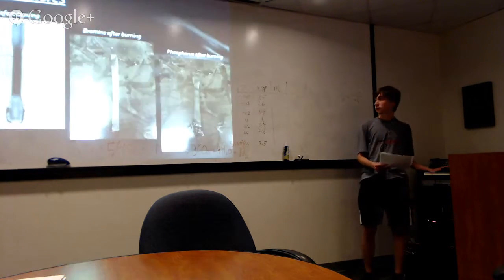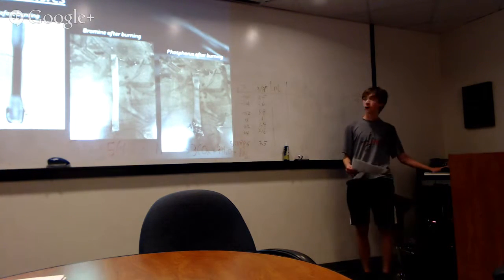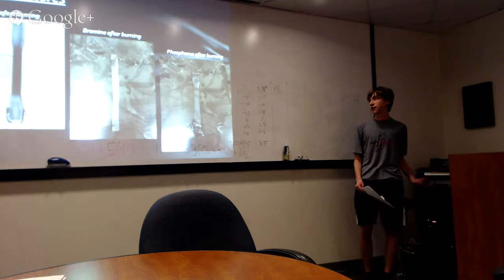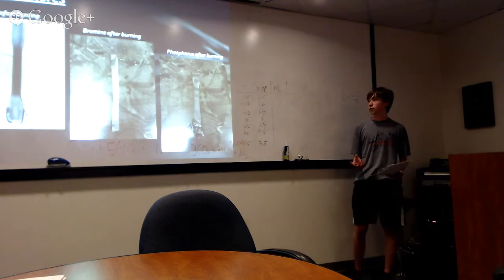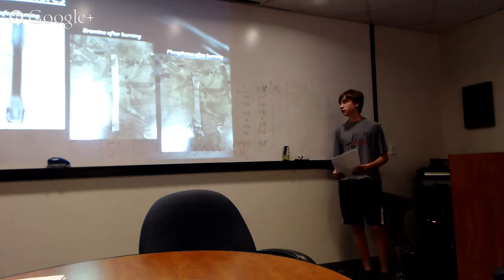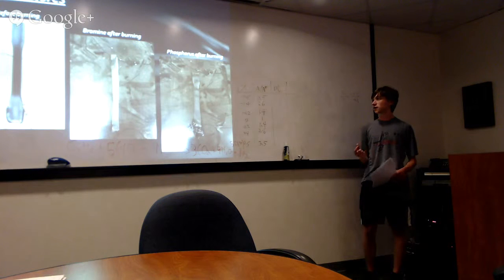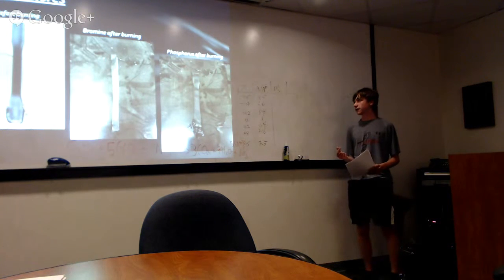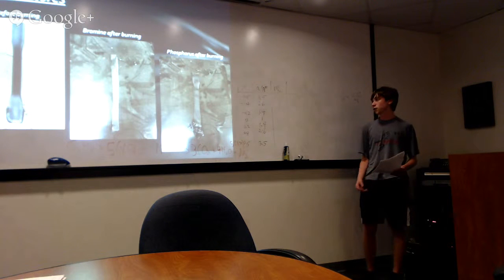So I'll go to the conclusions. The picture on the left is what the plastic looked like beforehand, which was being burned right there. The one in the middle is one of the bromine flame retardants after burning for 10 seconds. You can see on the top there's only a slight amount of burning after 10 seconds, and it didn't really fall apart. It worked very well in the fire.